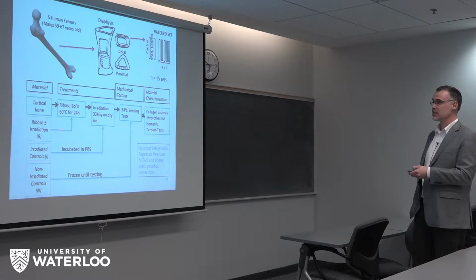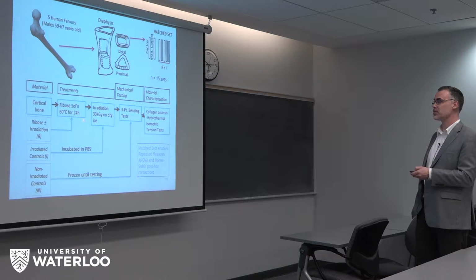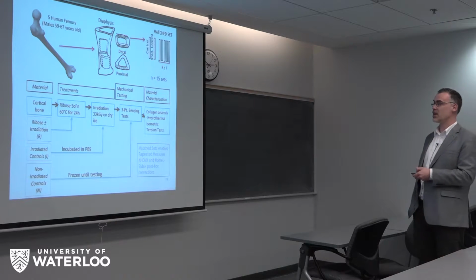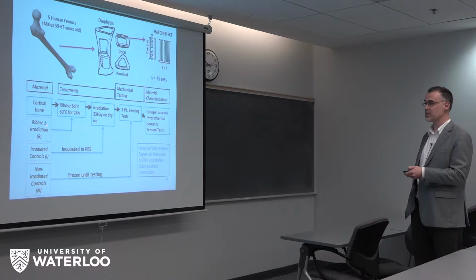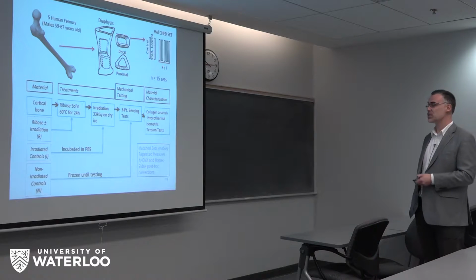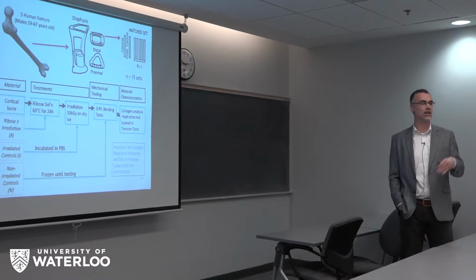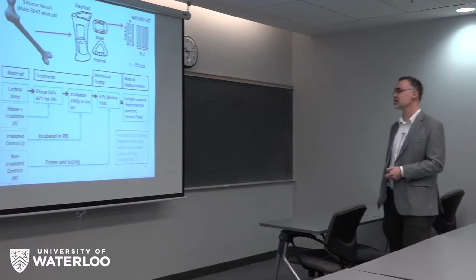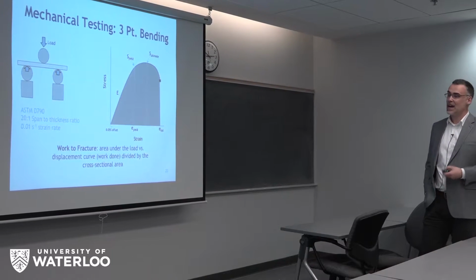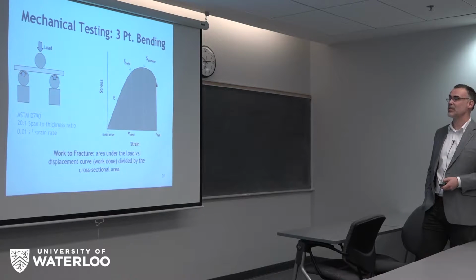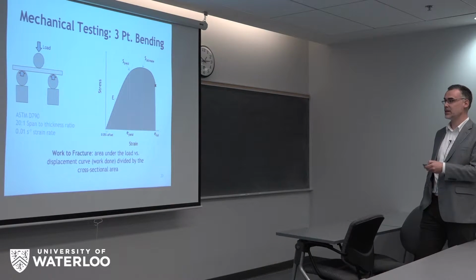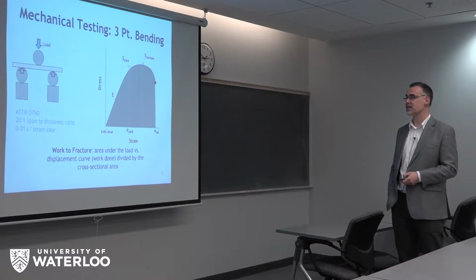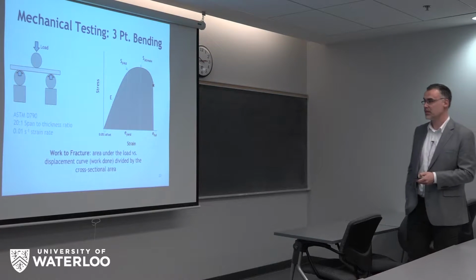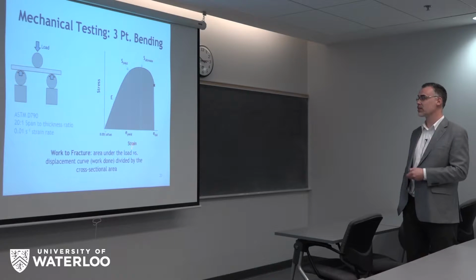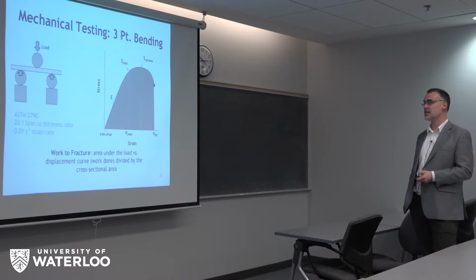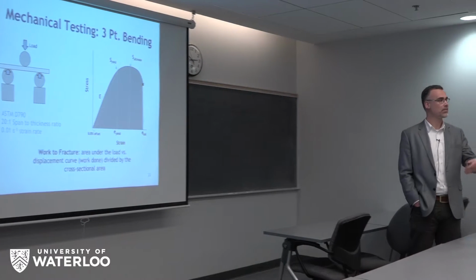And so this is sort of the experimental design: cortical bones treated with ribose, irradiated, and then we did our mechanical testing and collagen analysis for connectivity. And we had multiple ribose groups, plus or minus irradiation, and our controls. So we use match sets to enable us to control for inter-location and inter-donor variability, because that's quite significant. And we did 3-point bending after the specimens returned from gamma radiation, and we follow an ASTM standard that other people in the literature follow. 3-point bending is not ideal, but it gives us a starting point for the mechanical testing, and we measured things like elastic modulus, strength, ductility in terms of strain to failure, and work to fracture. So how much work did it take to break the beam divided by its cross-sectional area.